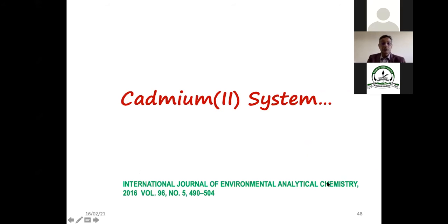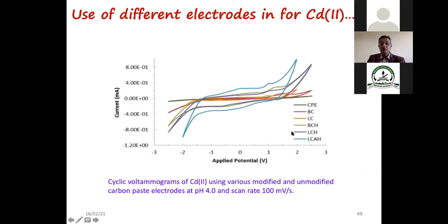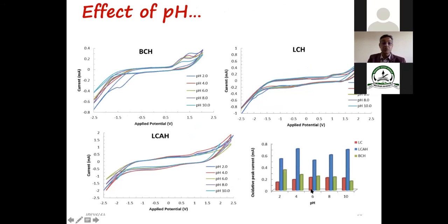Now we try some of the cadmium-2 system. This data was published in the International Journal of Environmental Analytical Chemistry, 2016. Here we are not getting sharp peaks, but even then some peaks are coming. Cadmium is a 2 electron system, and we tried different materials and different pH also. You can see that pH 4 and pH 10 are good. At around pH 4 we get a very good signal for cadmium, so we conducted most of the studies at that particular pH.